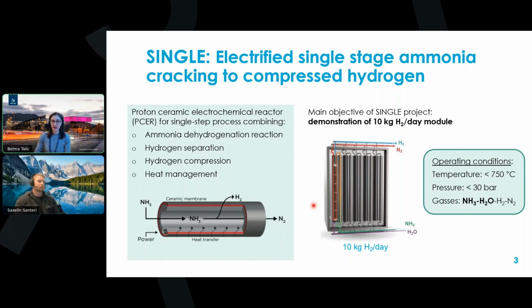The reactor itself and the module will be operated at temperatures up to 750 degrees centigrade, aiming to deliver hydrogen up to 30 bars. Because of this proton conducting membrane, the proton conductivity of the membrane relies on humidified feeds. The system will be exposed to wet ammonia containing gas mixtures.